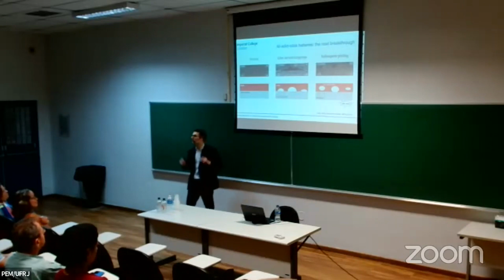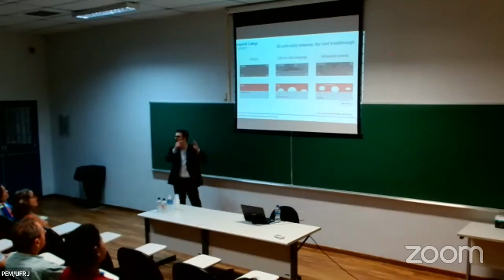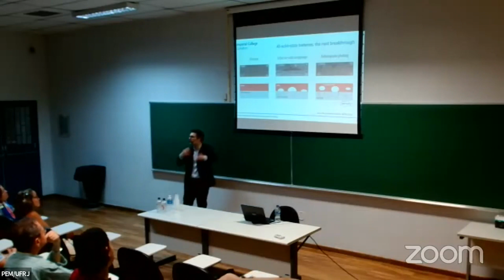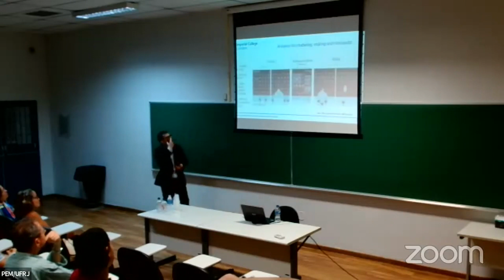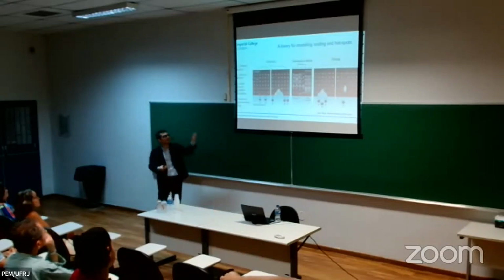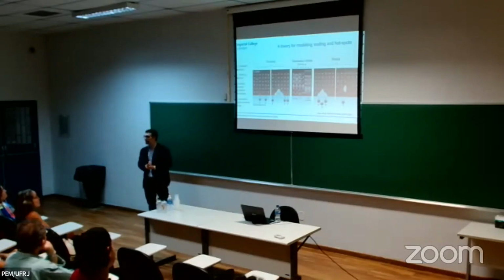And being able to capture the evolution of these voids is critical, because at the edges of those voids, you get what we call current hotspots. These are localized regions where the current is very high, and because the current is very high, during plating, that's where you deposit the lithium and you get the dendrites. So if you can eliminate the hotspots, we eliminate the dendrites. And in order to eliminate the hotspots, we need to understand how those hotspots are generated in the voiding system. So we need to simulate how those voids grow, under which conditions, and so on. And this is quite an interesting, I would say, multi-physics problem that again has a complex interface involved. In this case, the interface is not a crack, it is those voids in the lithium metal, but this is what we try to simulate. So again, a suitable problem for a phase field multi-physics model.